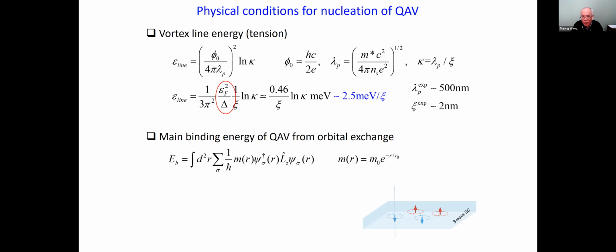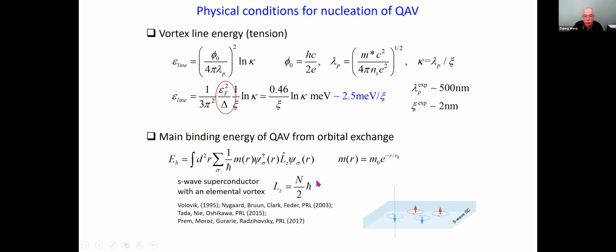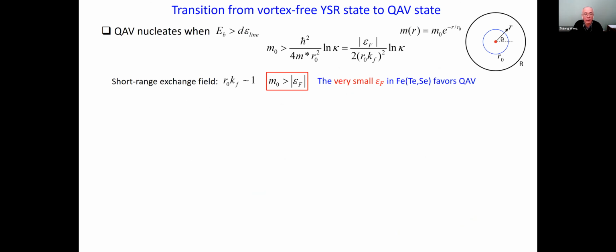Now, the second thing, of course, is the core energy. The core energy is what you pay usually, but because of the strong spin-orbit coupling, you actually gain this energy. This is what gives the Lorentz force. And you can estimate this because we know the total angular momentum of an elemental vortex is the number of pairs times h bar over two. And now you can estimate the energy from the binding part. Now, when these two become comparable, you have a quantum anomalous vortex nucleation. So now when the binding energy becomes larger than the line energy, you get this equation. And for a short-range exchange field, you see that all you need is the exchange coupling to be greater than the Fermi energy. And the very small Fermi energy, 4.5 meV for FeTeSe, is what's favoring this quantum anomalous vortex.